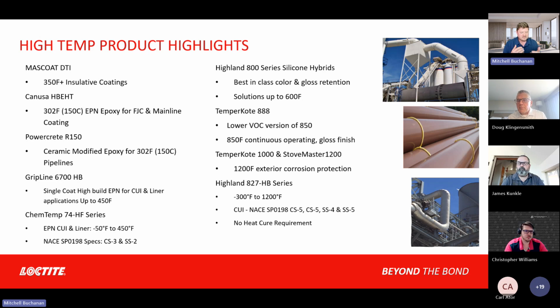And for that one, your immersion service is, depending on the chemical, going to cap out at 300 or 350 degrees Fahrenheit. Dry heat is going to be 450 Fahrenheit. So this is an epoxy Novolac type chemistry. And then one step up from the Gripline 6700, we have ChemTemp 74HF, which is also a CUI coating and a chemical resistant liner, 450 Fahrenheit dry heat, 300 up to 350 Fahrenheit for immersion service and a lot of chemicals. Some of them, your more aggressive acids, will cap out at 250 or 300 Fahrenheit, but things we can discuss with you as an asset owner. And it does meet the SP0198 specs for CS3 and SS2.